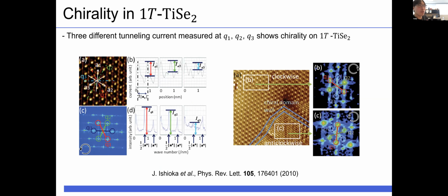Recently, chirality beyond the known structure has been an issue in 1T titanium diselenide. STM data measured by Ishioka and collaborators inferred that the inversion symmetry is broken in this material. They found a superlattice structure here, and they found that the tunneling current along the 3 different directions has a different modulation. This is the image, and this is the line cut. They did a Fourier transform on this image. The result is figure C. And there is a certain direction in which the CDW peak increases. Here, it's counterclockwise. So this observation can be interpreted as due to chiral symmetry breaking at low temperature.